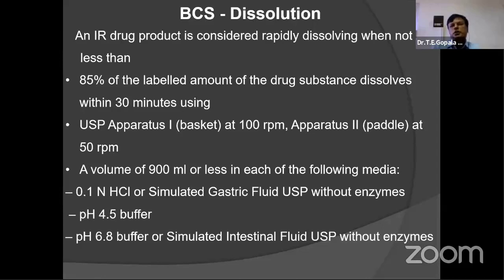An immediate release drug product is considered rapidly dissolving when not less than 85% of the labeled amount of the drug substance dissolves within 30 minutes using USP apparatus 1 at 100 RPM or apparatus 2 at 50 RPM. In case of paddle, it should be conducted at 50 RPM, and in case of basket, it should be 100 RPM. Then how much volume of the dissolution medium? Maximum it will be 900 ml, and in some cases you may go for even 500 ml depending upon the sink conditions. And the drug should dissolve 85% in any one of these dissolution media. Either it may be 0.1 normal hydrochloric acid or simulated gastric fluid without enzymes, or pH 4.5 buffer, pH 6.8 buffer, or simulated intestinal fluid without enzymes.